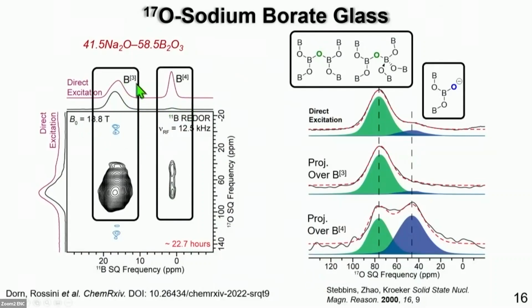And if you look at the oxygen projection over the BO3 group, you can see that it correlates to 2 NMR signals previously assigned to bridging oxygen atoms shown in green and non-bridging oxygen atoms shown in blue. Now, when you look at the projection over BO4, what you can see is that it correlates to the expected bridging oxygen atoms, but it shows very intense correlations to the oxygen NMR signal previously assigned to a non-bridging oxygen.